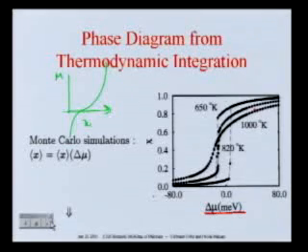And you see, things get interesting when you start being below a critical temperature. So you see, we got 820 Kelvin, and you really see that the curve is still continuous, but it starts to have a slope in the middle that is going towards infinity. And if we go below, at 650 Kelvin, what happens is that we have opened a miscibility gap.